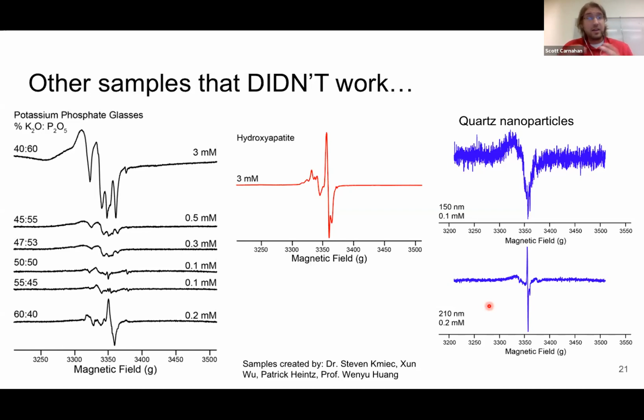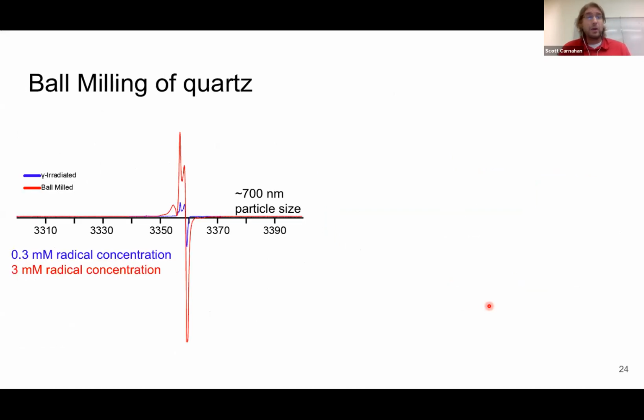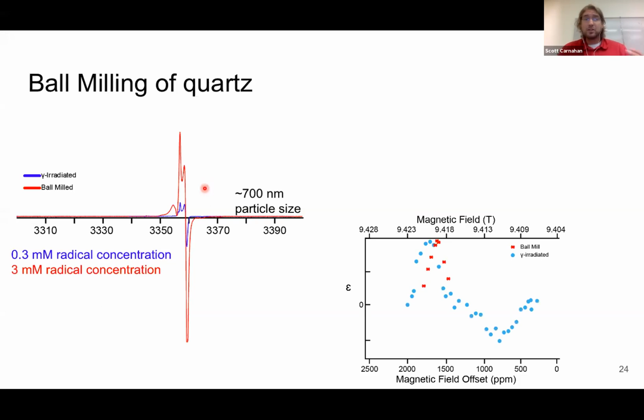Instead of synthetically making them small, let's ball mill a large sample. When we did that, we actually found we had more radicals after ball milling than if we just gamma radiated the sample. So particle size wasn't quite as small as we were hoping, but what we did get was a large influx of radicals, and we were able to do DNP with these.